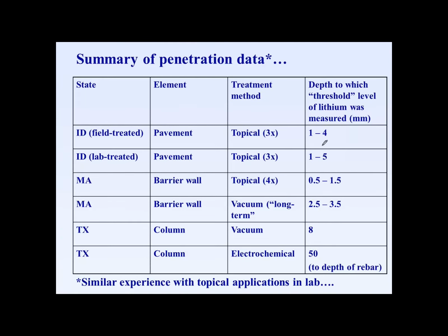And as we saw with all the topical applications, it was very minimal and certainly not enough to result in any benefit. And the same could be said for the vacuum applications as well. But the positive note here was we were able to drive the lithium all the way down to the surface of the steel.